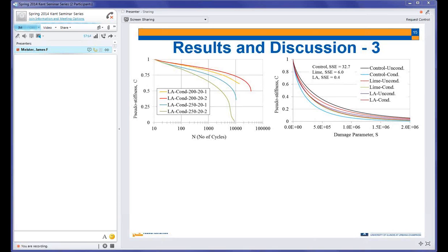Again, we have 6 curves because we have 3 mixes and 2 conditioning sets, unconditioned and conditioned. And as you can guess, the higher the curve, the better the performance, because as we increase the damage, the decrease in the stiffness is less, which means that the material still resists damage more. If you look at only the unconditioned state mixes, the ranking is control, then lime, then liquid anti-strip. You still remember, this is the same ranking that we got from the Lottman test, looking only at the unconditioned tensile strength. If you look at the conditioned, after 5 freeze-thaw cycles, the ranking is liquid anti-strip, lime, control.